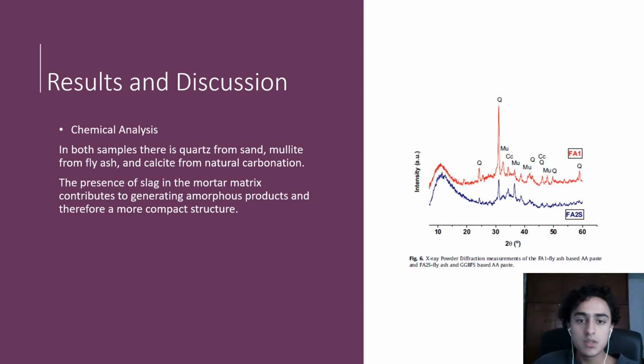Results. Chemical analysis. In both samples, there is quartz from sand, mullite from fly ash, and calcite from natural carbonation. The presence of slag in the mortar matrix contributes to generating amorphous products and therefore a more compact structure. In the figure, you can see the results for the X-ray diffraction for the samples FA1 and FA2S.